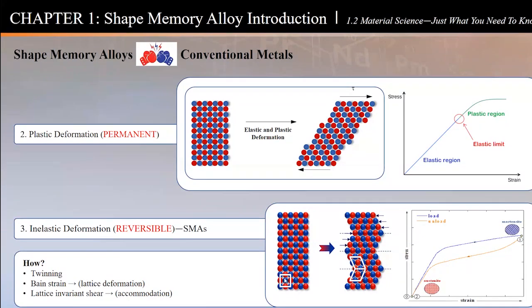So when you apply heat or you deform it, or you cool it or you deform it, it goes to this sheared kind of geometry. So these planes just shear like this zigzag, what we call twinning. The term for it is twinning. But in this process, there are no broken planes like you see here, where you break a plane and it's permanent deformation. This deformation here, enabled by the twinning principle, is reversible. So I can go from here, load and unload, or heat and cool, and so on, from this little representation of the cubic austenite phase to this little representation of some other lower symmetry martensite phase.